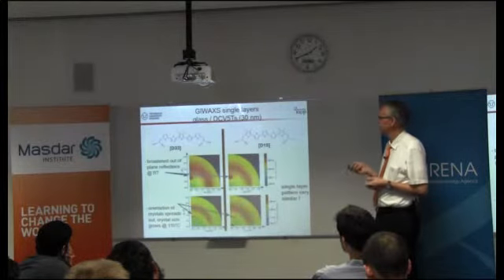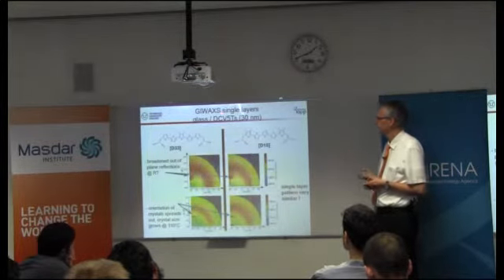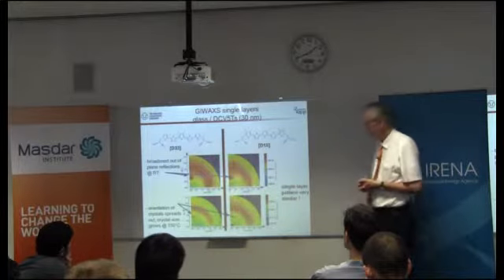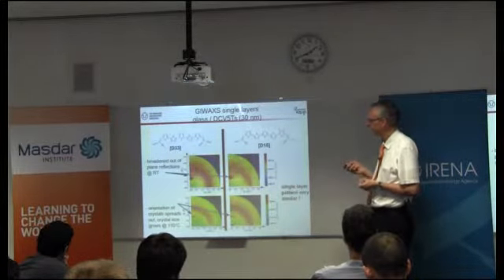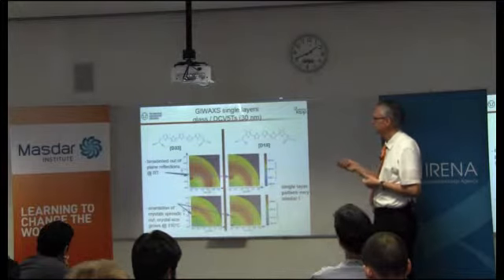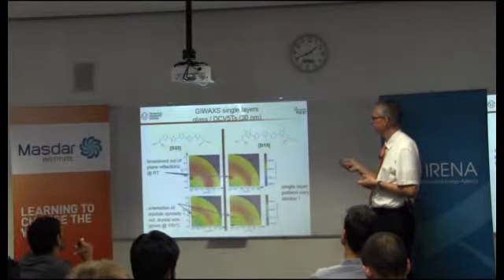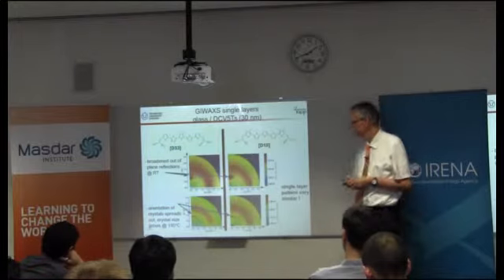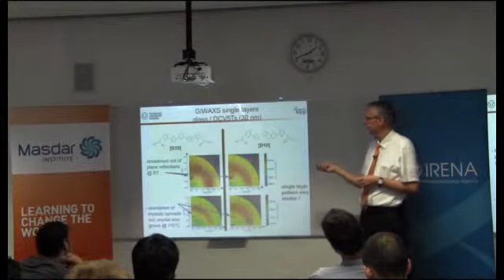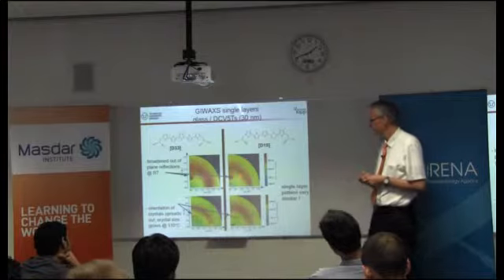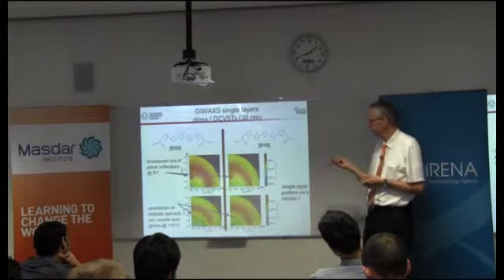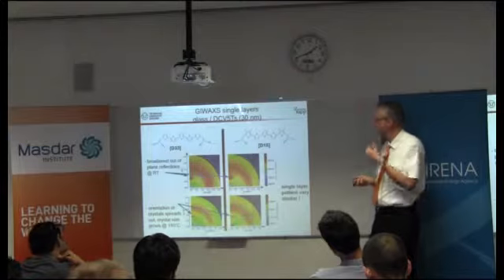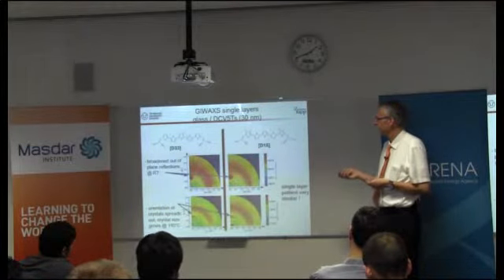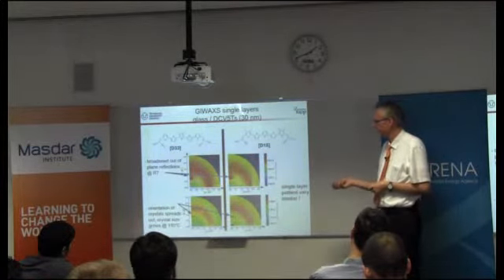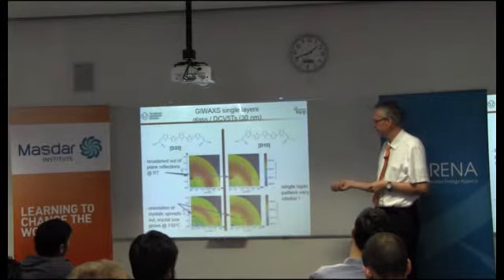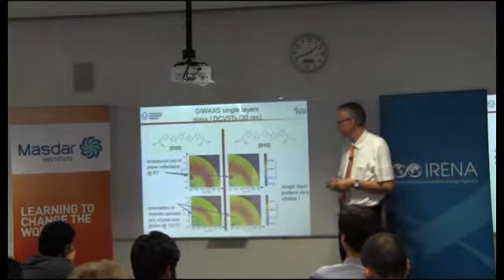We obtained these data because one of my students did measurements at the synchrotron in Stanford, grazing incident wide angle scattering, and again systematically comparing layers of these different molecules. And at room temperature he gets pretty broad reflection, so at room temperature both these molecules grow fairly disordered, close to amorphous. At somewhat higher temperature, in this case 110 degrees, the peaks narrow, and there seems to be quite good ordering.